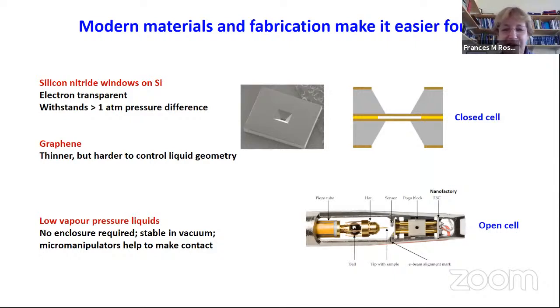So this is an SEM picture of a typical window chip. It's a silicon nitride window on silicon. The way you make these chips is that you start with a silicon wafer. You deposit silicon nitride, typically on both the top and the bottom surface of the wafer, and then you pattern some holes on the bottom surface, etch away the silicon nitride, and then etch through the silicon to the top surface, which is underneath in this image, and you control the etching such that the window, the silicon nitride, is preserved.